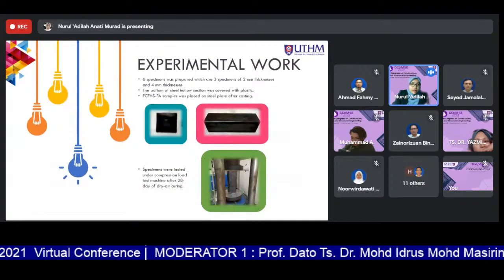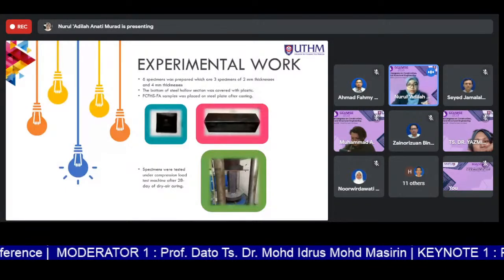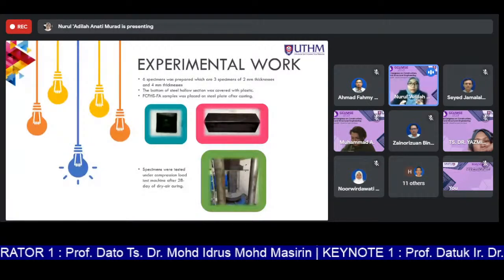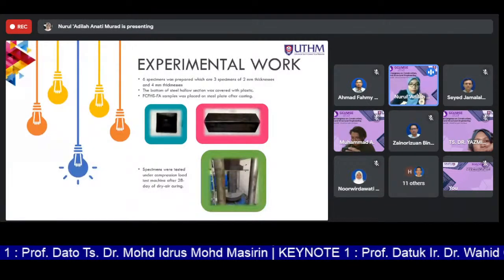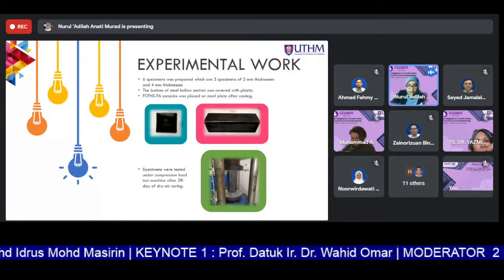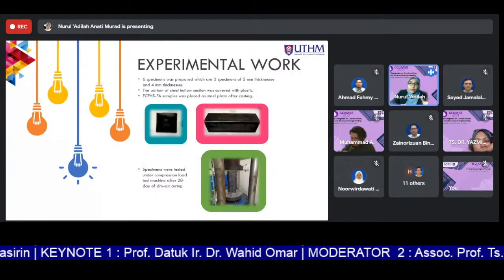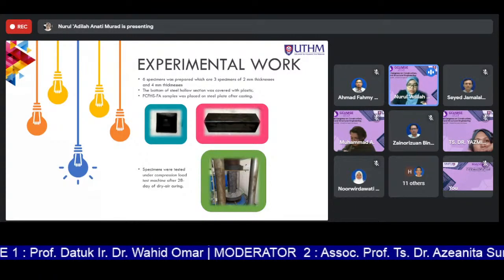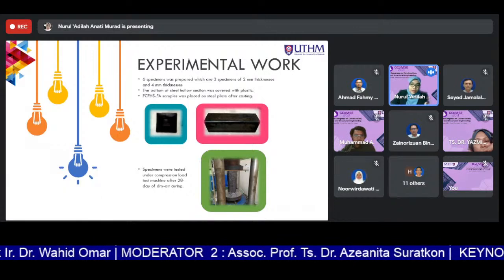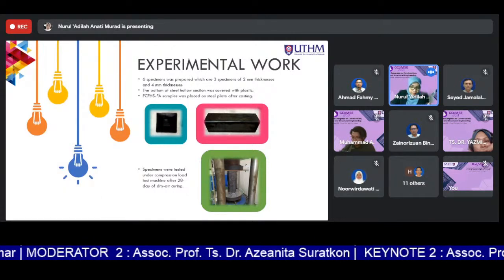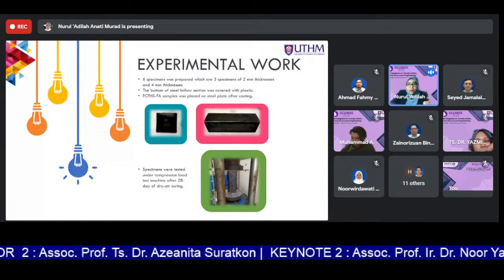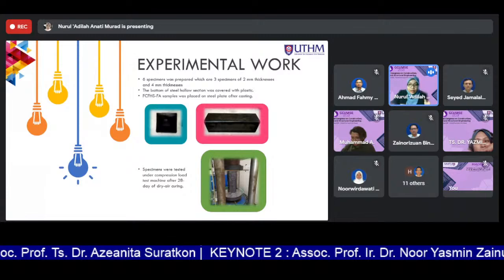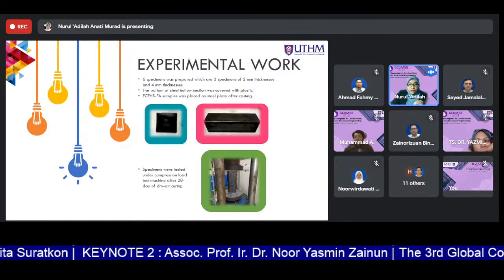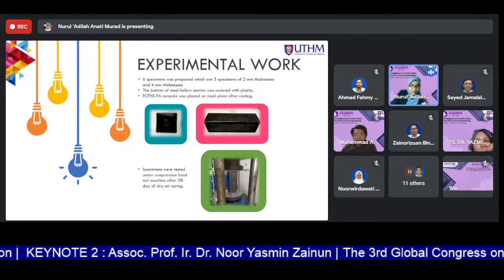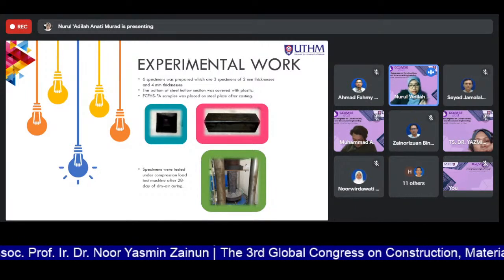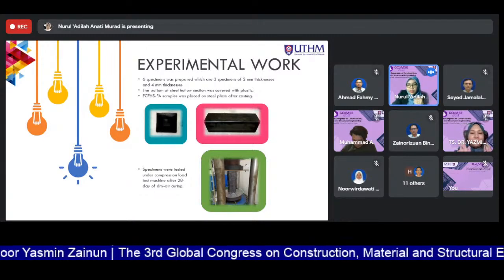Okay, for the experimental work, 6 specimens were prepared, which are 3 specimens for the 2 millimeter thickness and 3 specimens for the 4 millimeter thickness. And the bottom of the steel hollow section was covered with plastic to avoid the concrete water flowing out from the bottom of the steel hollow section. And the modified foam concrete hollow section using fly ash as sand replacement specimen was then placed on the steel plate, following the concrete casting for these 6 specimens. And the specimens were tested under compression load at 28 days after the dry air curing method. Sorry.